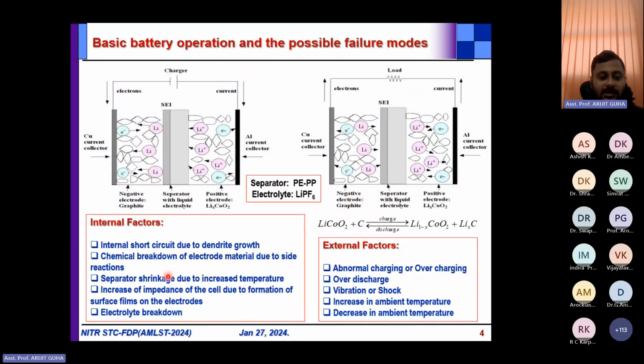catastrophe event. Now another thing that I have shown here is the chemical breakdown of electrode materials due to side reactions. Side reactions happen inside a battery, and due to that there can be a chemical breakdown of the electrode material, the material with which the electrode has been made. Here it is lithium cobalt oxide. So if there is a breakdown, there can be some internal fault inside a battery. It also depends on temperature. Temperature is a very important factor. With increased temperature, the separator has a certain limit, and at higher temperatures there is a tendency that it may melt. Due to that melting there can be some shrinkage, which can also be an internal factor of battery failure.